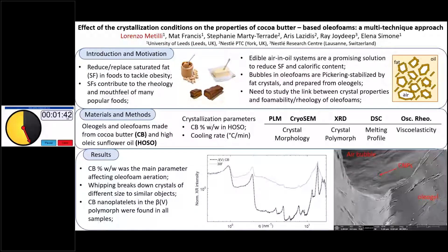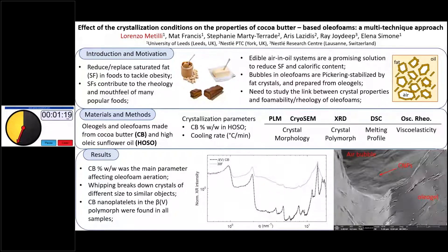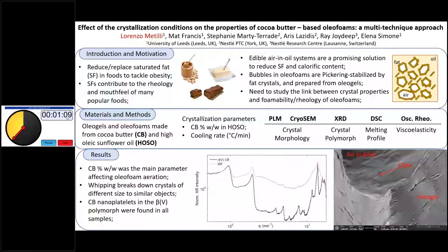In my project, I prepared several oleogels by mixing cocoa butter and sunflower oil in different ratios and using different cooling rates. I used the techniques shown in the slide to study the materials, especially their crystalline properties. The results showed that the main parameter affecting the properties of the oleofoams was the amount of solid material, because regardless of the cooling rate, the aeration step breaks down the cocoa butter crystals to objects of similar size, eliminating differences due to crystallization conditions.